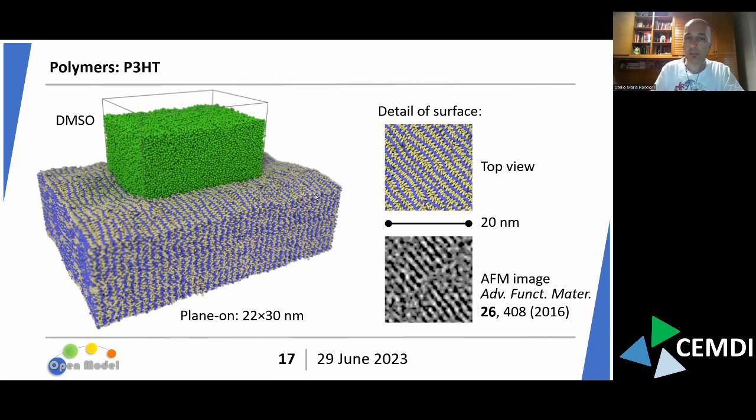But interestingly, if we look at the morphology of this planar configuration, there is apparently a way to produce this surface experimentally, and this is a one-to-one comparison between an AFM image showing that particular crystal surface and the corresponding model. If you count, it's the same number of stripes, and they are exactly on the same scale. So quite a nice proof that with good coarse-graining, you can indeed access a number of interesting properties.